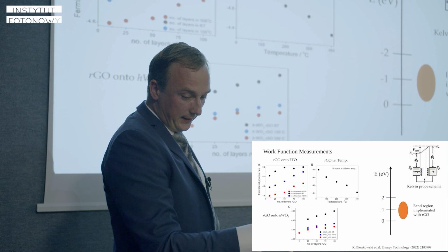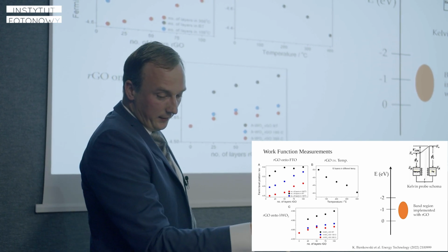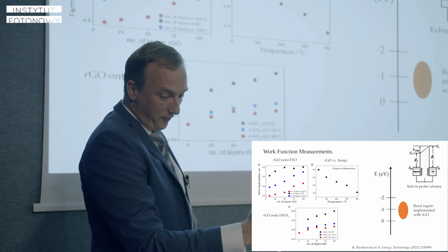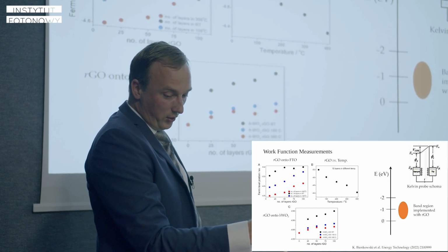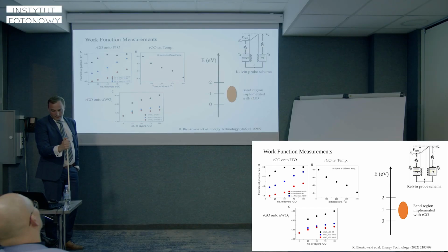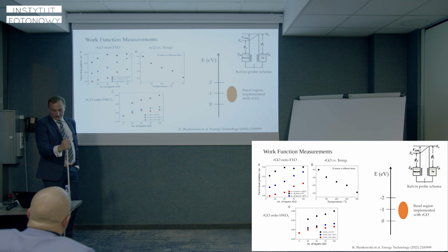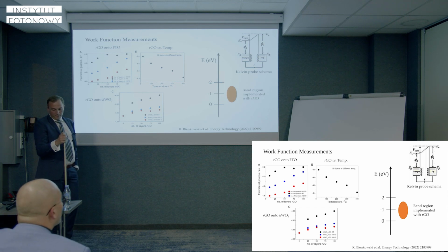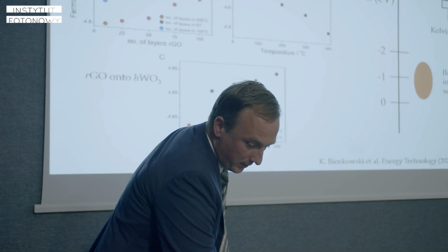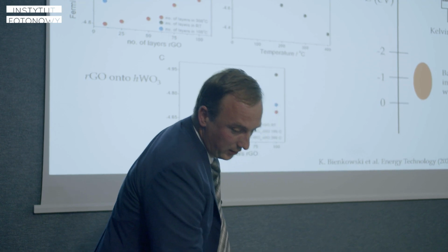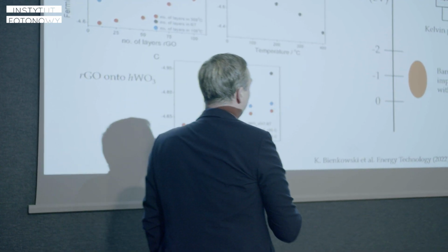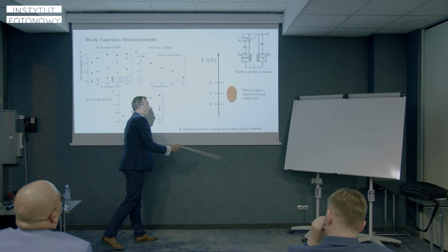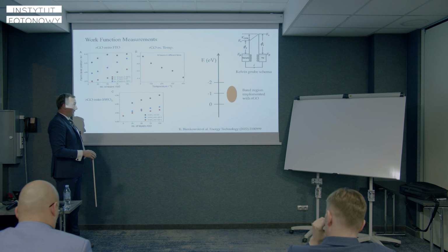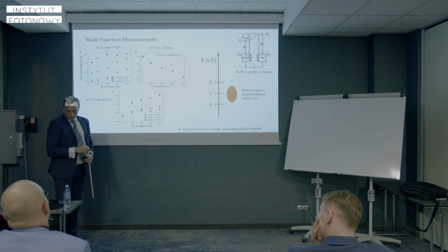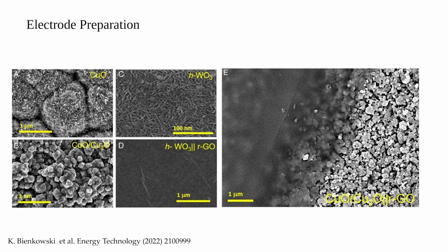Our measurements clarify that increasing the number of RGO layers drives the Fermi level towards more negative, and the observed shift in the Fermi level position can be attributed to two phenomena. The first phenomenon is rooted in the GO and RGO synthesis. As the graphene oxide is heated, functional groups are eliminated and the electrical conductivity increases. So to conclude this slide, we can make a deposition of RGO layers with a very specific work function, and we combine these results with our system. So we synthesize copper oxide.